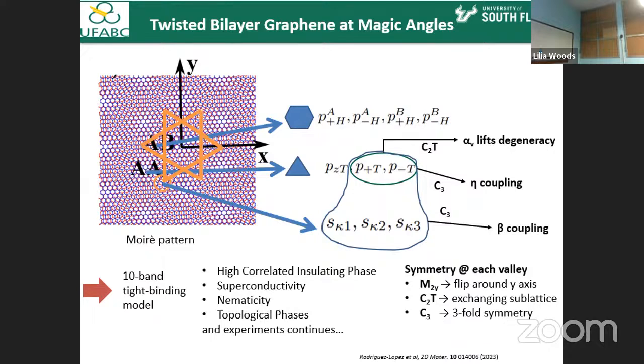One thing that is known, however, is that all of this is due to the strong effect of high correlation effects that are happening in the flat band, but only for this particular angle. So correlation effects are very difficult to model analytically, say, by graphene, 3D or even carbon nanotubes. Very difficult. It's not easy to do that from first principles.